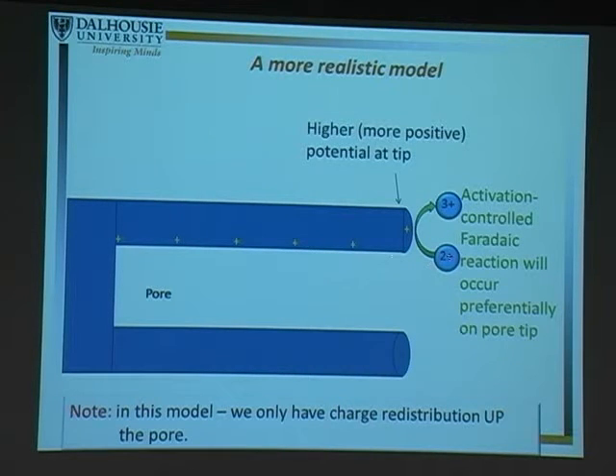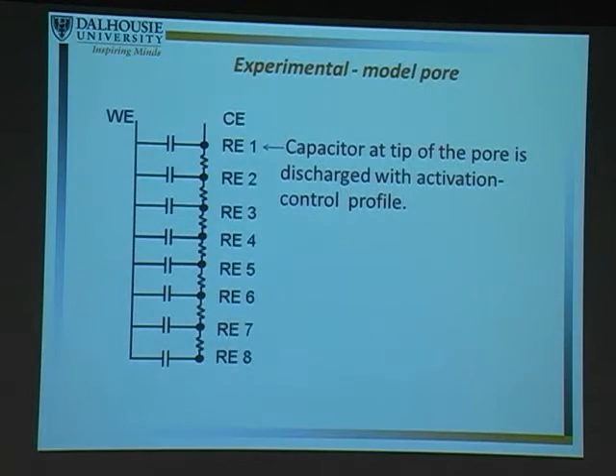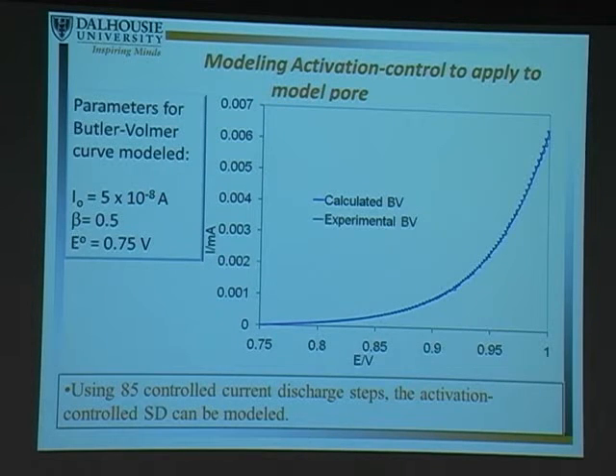So as we have our Faradaic reaction happening at the tip of the pore, it's going to start discharging the tip, and then will cause the charge to move back up the pore. So now we have charge redistribution going back up the pore. And so what we did was we went back to our transmission line model, and we're going to allow this to act as a pore with charge redistribution, and we're going to apply an activation-controlled type discharge at the tip of the pore, and see what our profile will now look like.